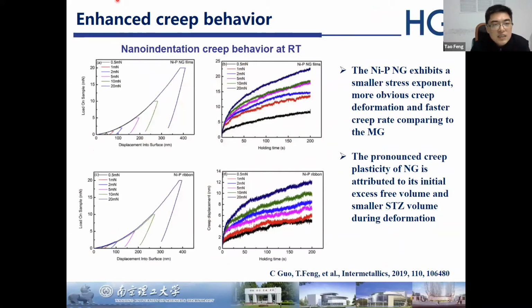And this nanoglass also shows enhanced creep behavior at room temperature. The nanoglass exhibits a smaller stress exponent, more obvious creep deformation, and faster creep rate compared to the metallic glass. And this pronounced creep plasticity of the nanoglass is attributed to its initial excess free volume and smaller shear transformation zone volume during the deformation.